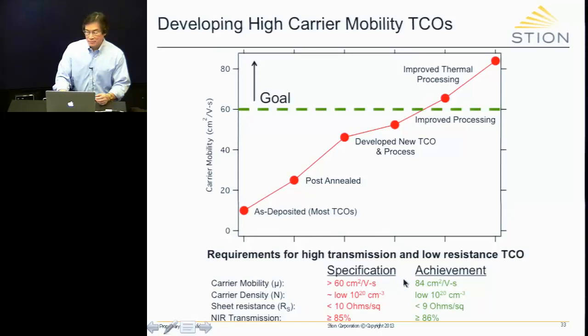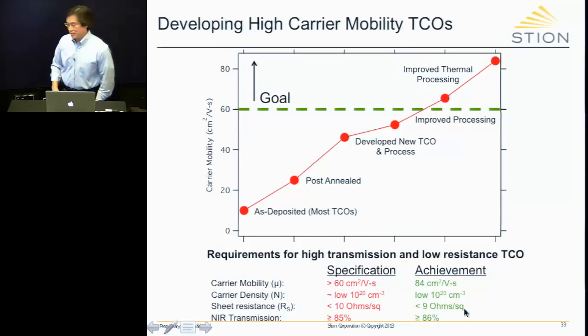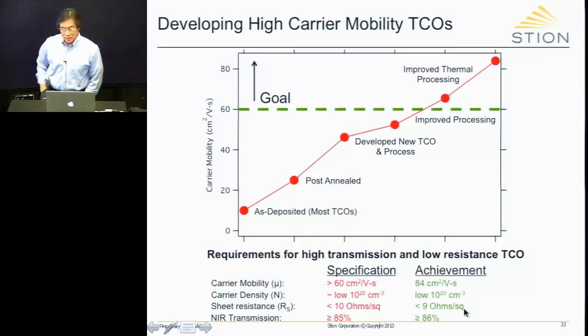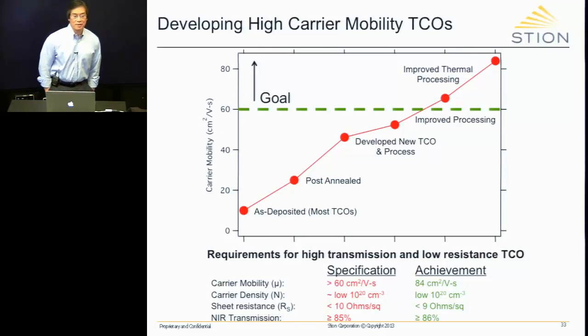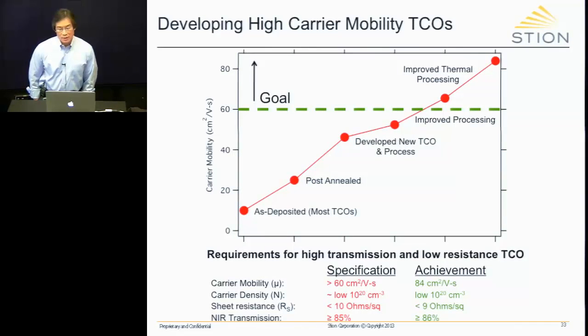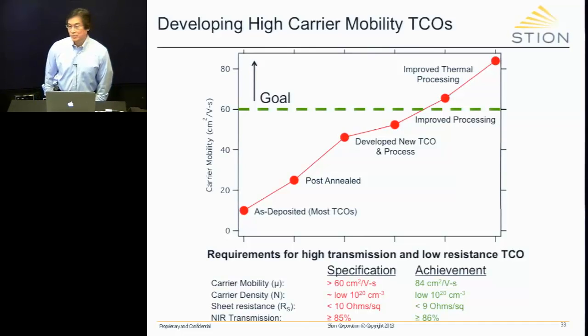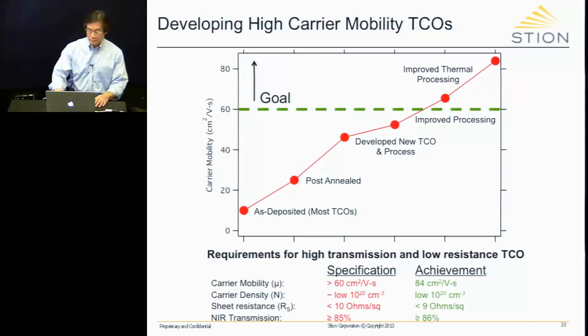Now, I should point out one more thing, and this has to do with the cadmium issue. There's a TCO out there that I absolutely love, and it has a carrier mobility on the order of 100 to 200 centimeters squared per volt seconds. It is based on cadmium oxide. It's a great material. I think NREL developed that. Cadmium oxide or doped cadmium oxide or cadmium zinc oxide. Those are great materials. The mobilities are very, very high. But the problem is with the cadmium. So we tried it. It works great. We get great results, but it has cadmium. It's a very thick layer of cadmium, no less. So that's a problem. Sorry.